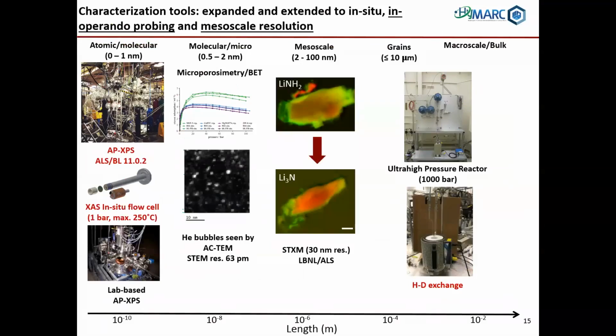Next slide. So characterization tools are also critical, and again, these match the length scales of the models, but we're using cutting-edge tools that were either not widely available when HyMARC started 3 years ago, or not available at all. Some of the ones illustrated here are soft X-ray tools at the Advanced Light Source, which allow us to probe coordination environments among light elements, but also very sophisticated electron microscope tools and X-ray microscopy tools, shown under the mesoscale column, that allow us to look at phase evolution. Then there are these more macroscale tools, such as a high-pressure reactor that provides a way of characterizing behavior under ultra-high pressures, in this case up to 1,000 bar. We can also look at the exchange of hydrogen and isotope effects, which help us look at the kinetics of the reaction of hydrogen with these materials.